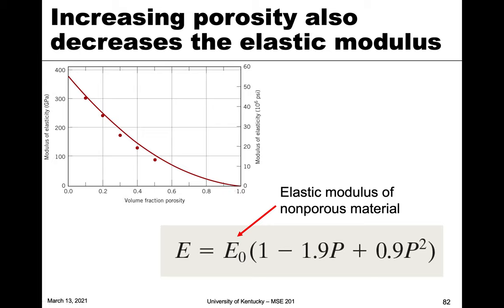Part of that decrease is due to the stress concentration effect, and part is because with less material there is less cross-sectional area — and since stress is force over area, more porosity affects that area term in the equation. So when we talk about ceramics and other brittle materials, the processing defects that occur become very important in controlling the mechanical properties of those materials.